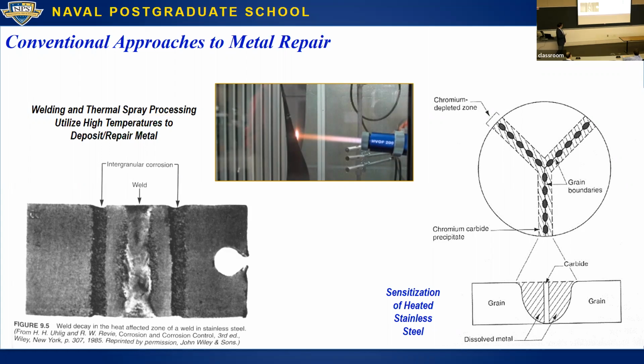And then the other more classical technique is welding. You weld something, and if you weld at very high temperatures, you can actually cause severe corrosion problems. So in this case, you have a stainless steel that has been sensitized. And when you weld something, you can sensitize it very easily. Basically what you're getting is precipitation of carbides that deplete the grains of chromium. The chromium, as you must all know, especially if you've taken a corrosion class, is added to essentially form a passive chromium oxide layer. That is what makes stainless steel stainless. And if you